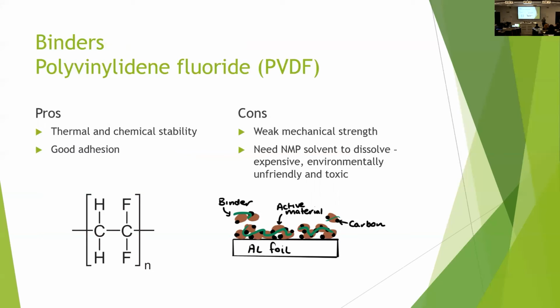But the con is that it has weak mechanical strength. Some battery materials, especially silicon, undergo really large structural changes during cycling, and PVDF isn't really mechanically stable. So what you end up with over a number of cycles is chunks of areas breaking off, and they become electrically insulated.